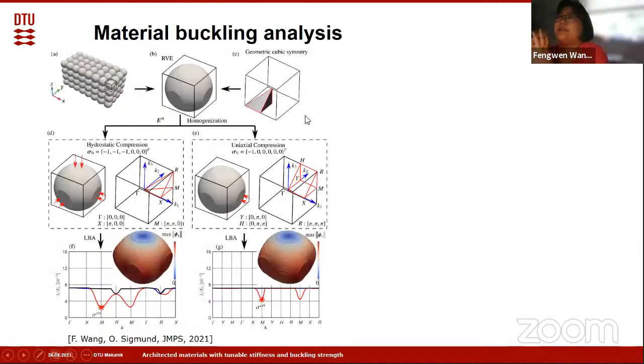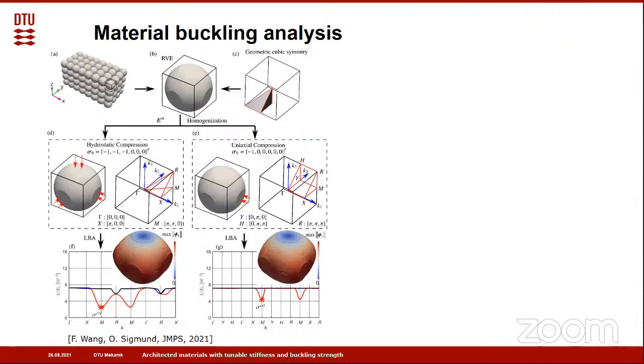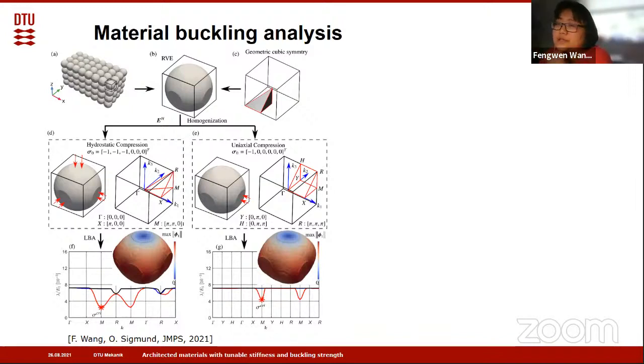For those who are not familiar with material buckling strength analysis, I first briefly introduce how we can evaluate material buckling strength using material buckling analysis. If we have a periodic material, we take these microstructures, then we employ a homogenization method to get effective material properties. Using the effective material properties, we can convert the macroscale stress situation to local stress situations, for example, here, hydrostatic compression or uniaxial compression. Then we perform linear buckling analysis to get the buckling factors, in order to capture both short wavelength and long wavelength buckling modes.